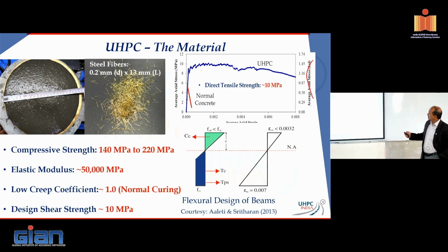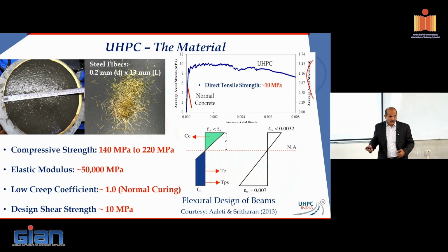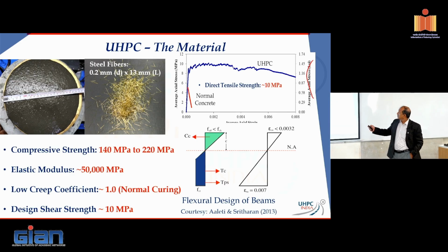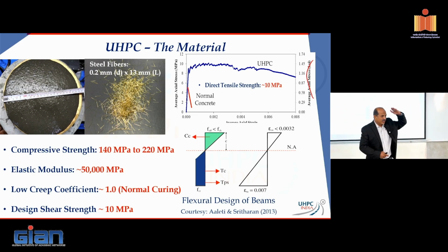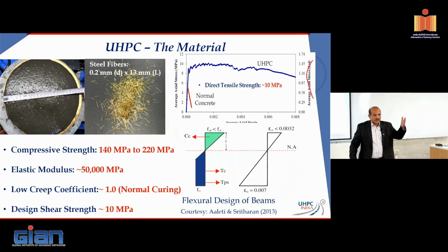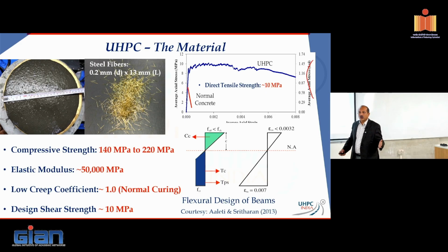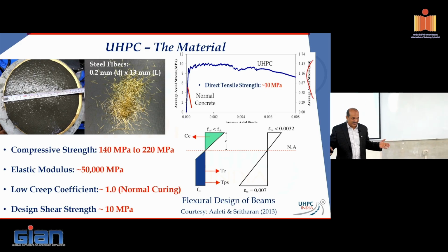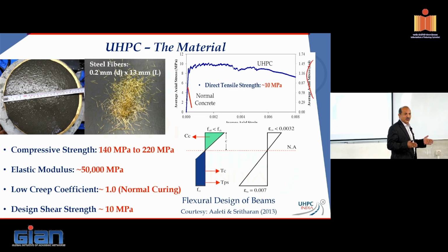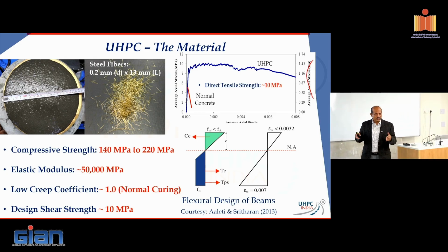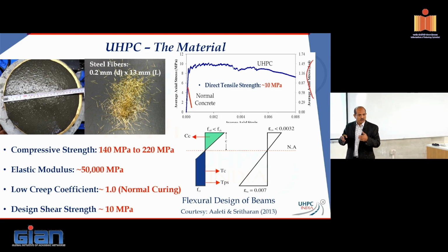Here's the beauty. This is typically your concrete. It will gain some flexural strength or tensile strength, and it will have a brittle failure. But due to the presence of these fibers, you have strain hardening behavior in UHPC. It's not so much strain hardening, you're not gaining strength, because it's at 2% right there. But if you start adding 3% by volume fibers, you will probably start seeing that strain hardening over there. And at that point, UHPC is probably going to be extremely uneconomical to use. Even at this point, you would not do 100% building in UHPC, it's not going to be viable. You're going to be selecting how you're going to add value to a project and solve problems in the project, and then utilize UHPC appropriately.